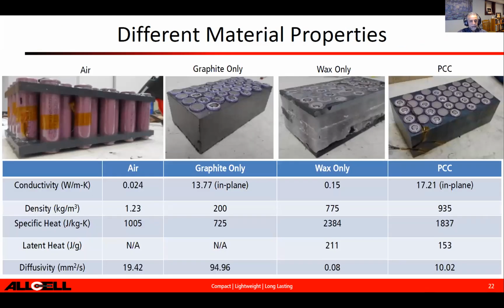Here's a summary of the designs that we've tested. The one to the left is air, then graphite only, then wax, and then phase change composite. And as you can see, the effective latent heat and the combination of that with high diffusivity is actually what makes the pack safe and what allows us to stop thermal runaway.